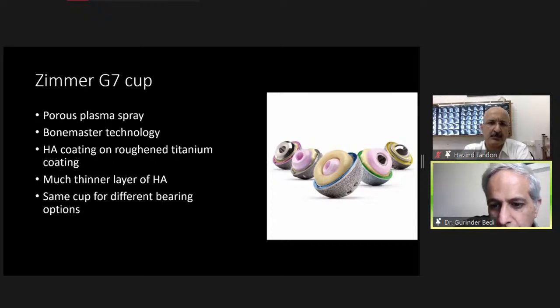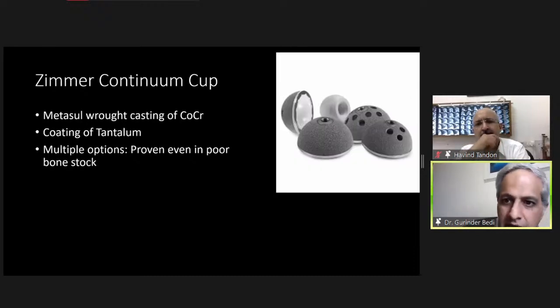This is the new kid in the market as far as Zimmer is concerned. A great cup. This was introduced, the G7 actually, simultaneously in all these countries, like a G7 group summit kind of thing. Porous plasma spray coating. They have a Bone Master technology, which is to say that there is an HA coating, but the HA coating doesn't smoothen the cup out. HA coating actually is a very thin coating, so the coefficient of friction, the roughness is still maintained. It's a very, very thin coating, but it actually is a very versatile cup. It takes a vitamin E poly, it takes a highly crosslinked poly, it takes a dual mobility cup, it takes a ceramic liner, everything it takes.